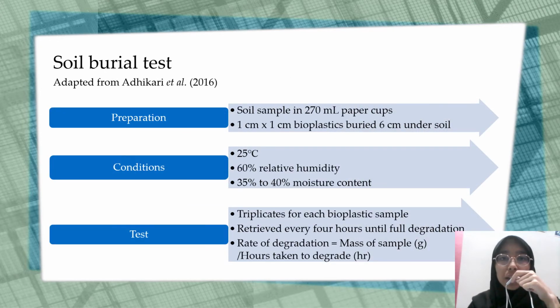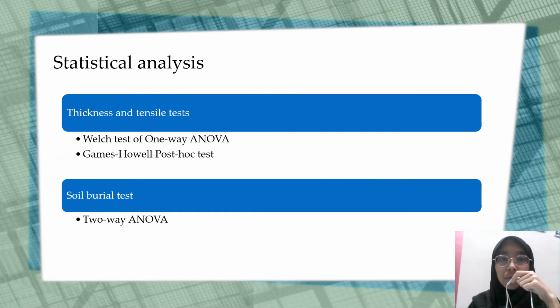The bioplastic samples were buried 6 cm under soil with the following control conditions. Each bioplastic sample was done in triplicates and retrieved every 4 hours until full degradation, and the rate of degradation was calculated using the shown formula. For statistical analysis, a value of P that is less than 0.05 is considered as statistically significant.